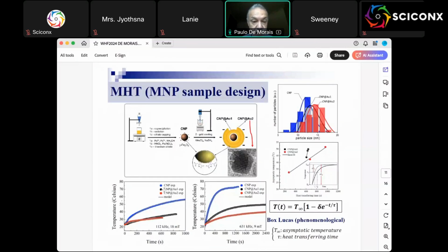However, if you look at the data with the thinner layer and thicker layer of gold on top, the asymptotic temperature goes below 40 C. So it does not even cross 40 C, and that is not desirable. Both conditions are not desirable.